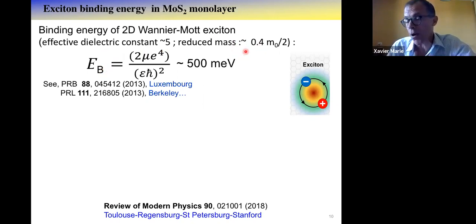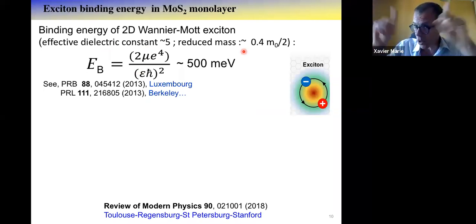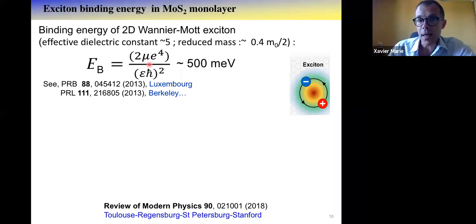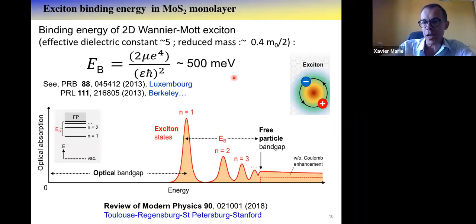The reduced mass is very important compared to, again, III-V or II-VI semiconductors. It turns out that the conduction band mass is rather heavy. At the end of the day, it will give you at the numerator a very large value, which will help to get a large binding energy. And more importantly, at the denominator, you have this dielectric constant squared, and this dielectric constant will be the key point. It is rather modest, and of course, it depends on the encapsulation environment. But very early, 7 or 8 years ago, you could put a reasonable parameter, and you end up with this very basic formula giving a binding energy of a few hundreds of millielectron volts.